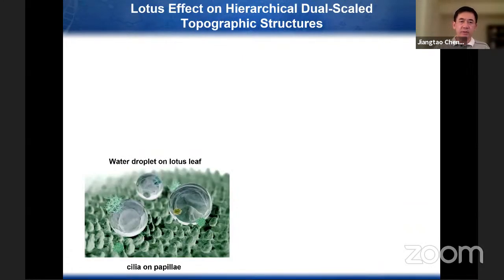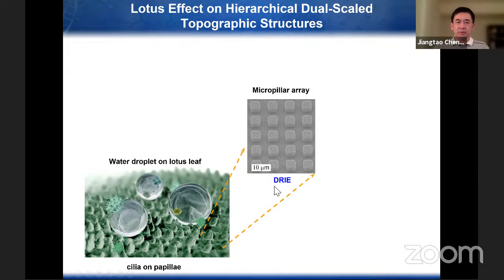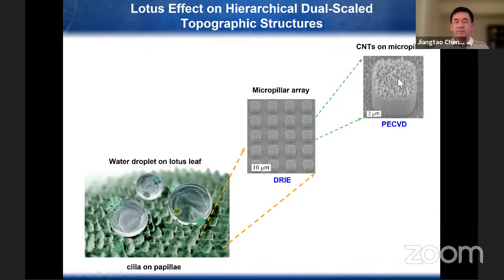In this work, we used biomimetic lotus leaf-like surfaces as the SERS platform. In the lotus leaf, there exist two-scale hierarchical structures. The cilia are the nanostructures grown on the papillae, and the papillae are micron-scale small hills. We used deep reactive ion etching to etch the micron-scale pillars, and then we grew carbon nanotubes on top of the micropillars. That formed hierarchical structures mimicking the lotus leaf-like surfaces, and these surfaces form the SERS platform.